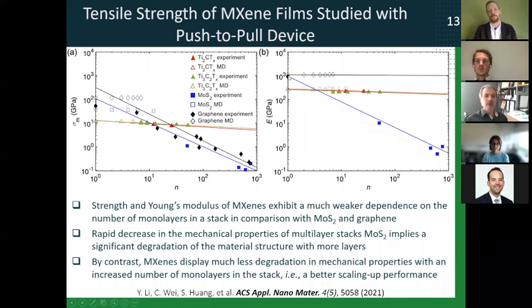Now, in terms of the Young's modulus, we don't have so many experimental data here, so we don't know how it actually goes, but modeling predicts that it should not degrade much, right? This is why we have this line here. For MoS2, we have experimental data which actually show that Young's modulus also degrades when we increase the number of layers, okay? So again, I think why they look different is because here we basically mainly plot modeling data. We don't have experimental information. And here we plot modeling, which shows, again, a horizontal trend, and experimental data, which show a decreasing trend. So I think the real effect, if you would have this data for the right-hand side, experimental data, would also show a decreasing trend, but we don't have the data at the moment.